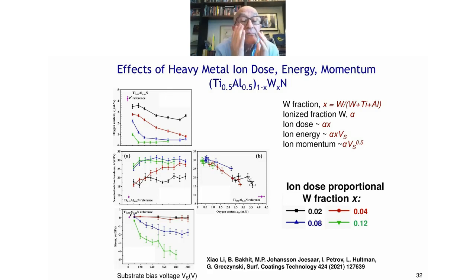Now, if you look at the oxygen concentration, the top graph, with small X of 0.02, we never get densification when we increase the energy. And if we go to the blue and the green curve, we get densification at about 100, 120 volts. The hardness, which is the middle panel, is high for the higher amounts of the higher dose.